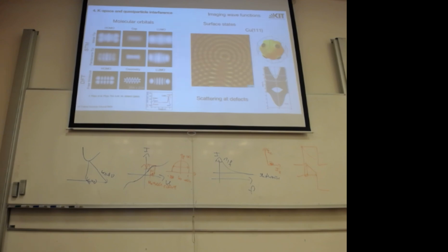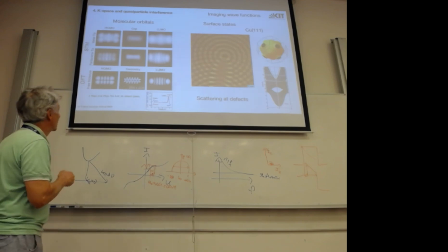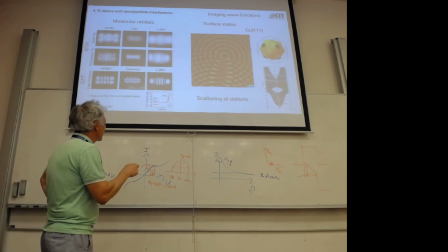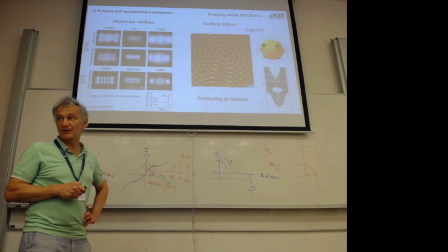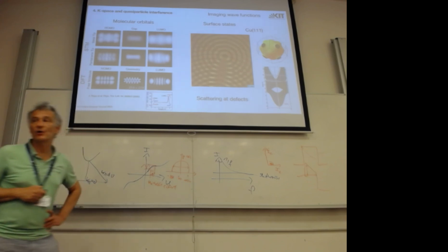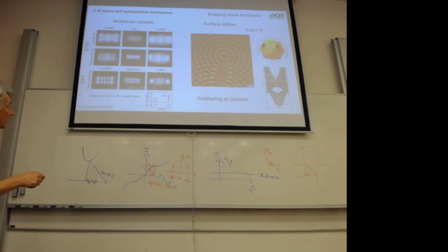Now these are examples. These are molecules. Same molecules, and there's a little tiny image here. This is the dI/dV spectroscopy. So you see a peak here, which is the lowest unoccupied molecular orbital, and a peak at negative bias, which is the highest occupied molecular orbital. And you can set now your STM to this bias voltage and record the dI/dV as a function of position.